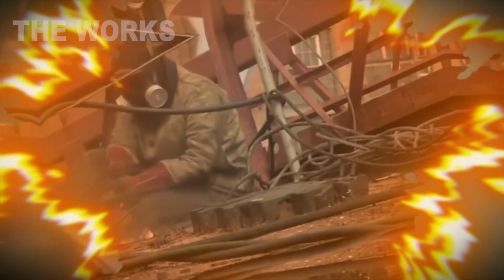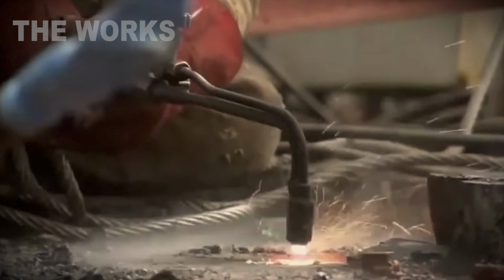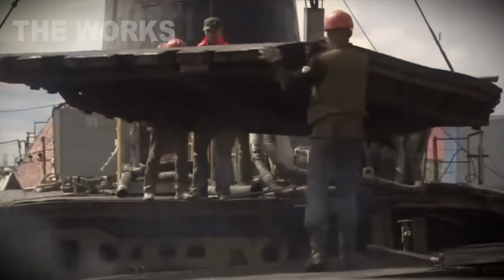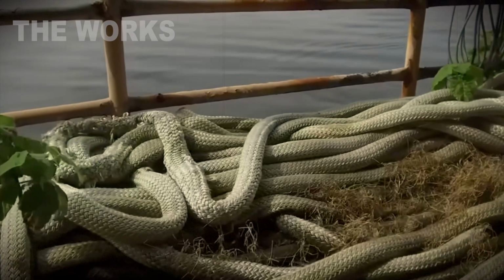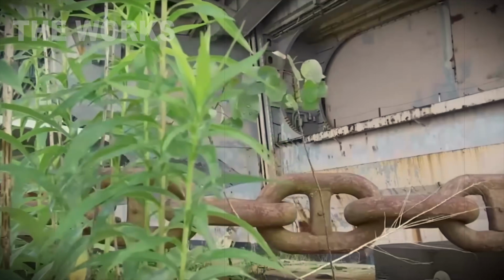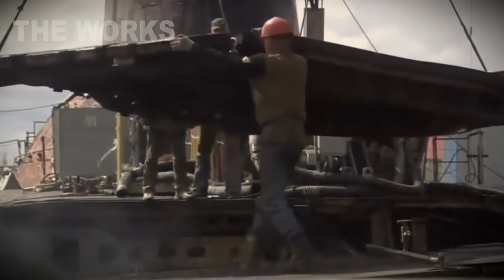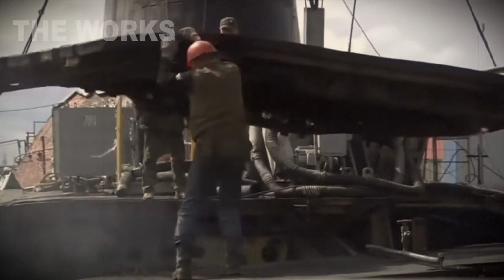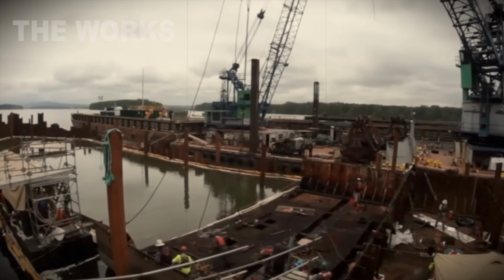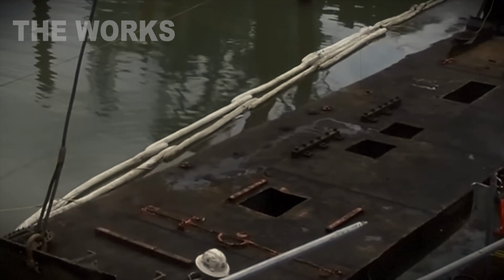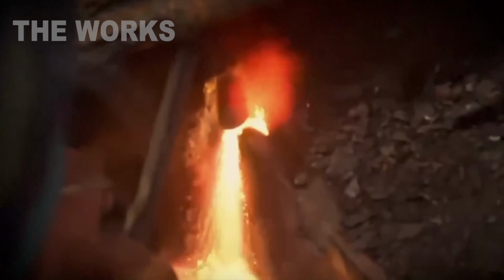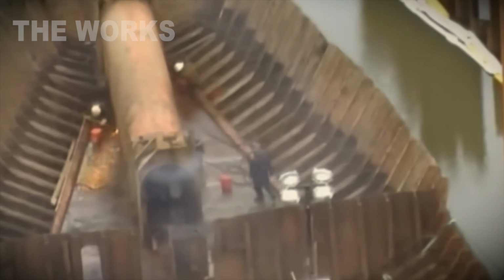Chemistry doesn't work everywhere. Valves, gate valves, filters, they dismantle those by hand. Teams of 3. Shifts last 30 minutes. Can't go longer, the dose accumulates. Every part gets packed in a lead box. Box weighs 265 pounds. Walls, 4 inches of lead. If contamination levels run too high, they encase the part in concrete right inside the hull.